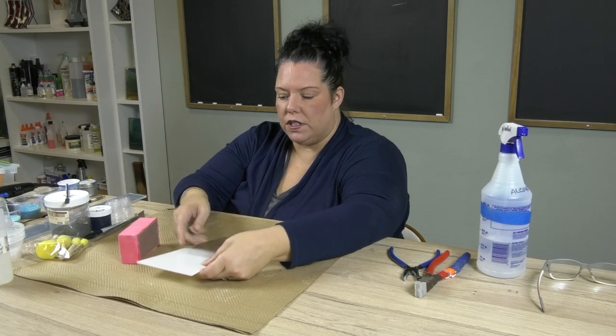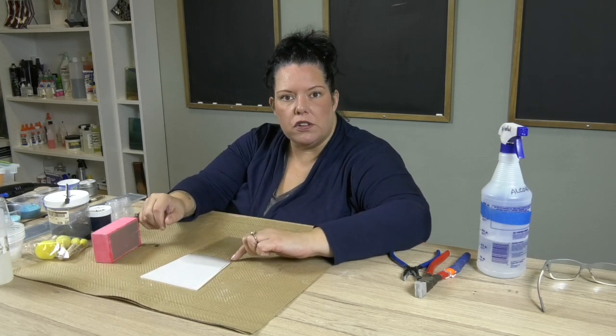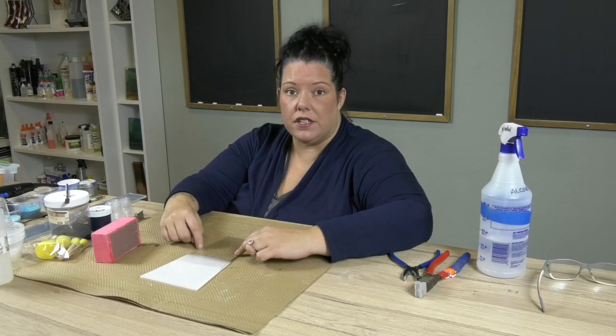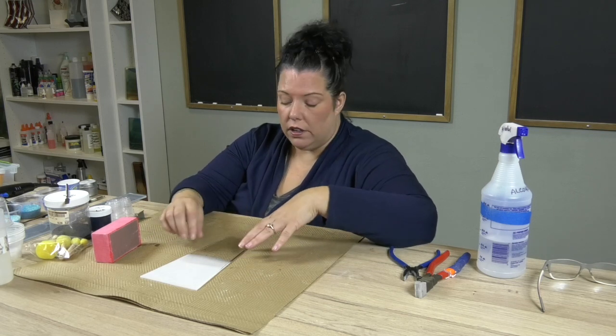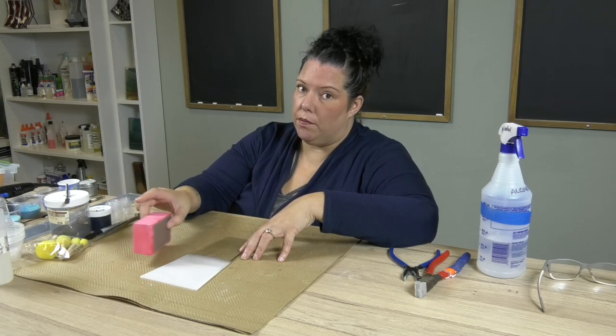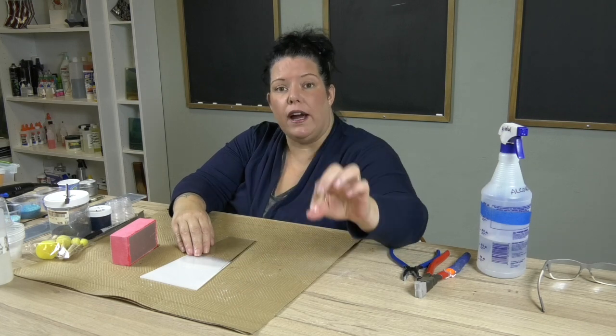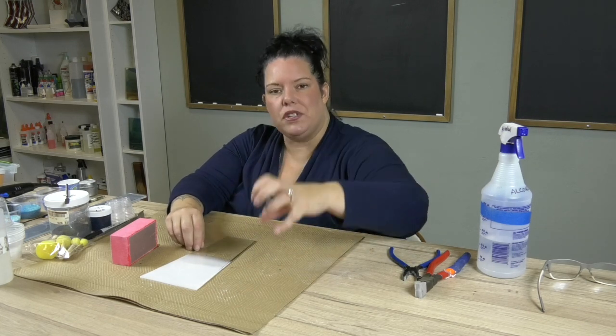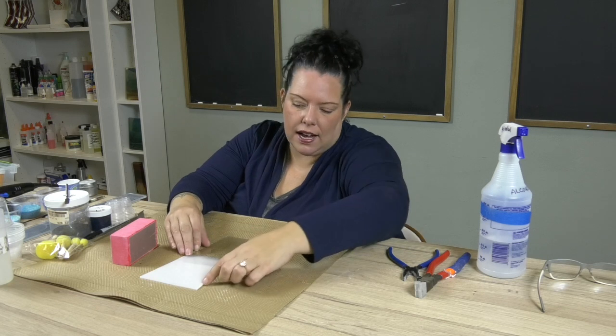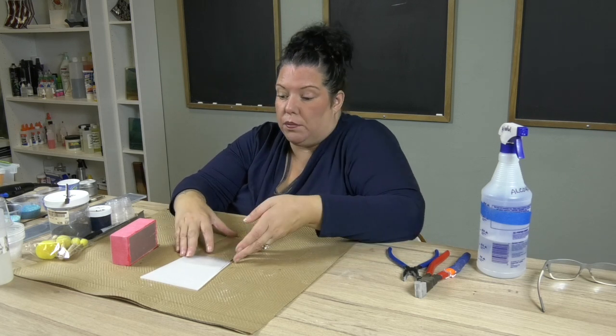So if this piece comes out after you cut it, and you've got little shanks and flares and things like that on the side, you've got to get them out. You can go to a grinder and kind of true this up, or you can use a diamond hand pad. If you go to a grinder, I don't have a problem with that, but make sure you are on a fine grinder head. If you're on a coarse or a standard, guys, it's not going to get enough temperature, and you're going to get those gray hazy lines on the side, and it's going to look terrible, okay?